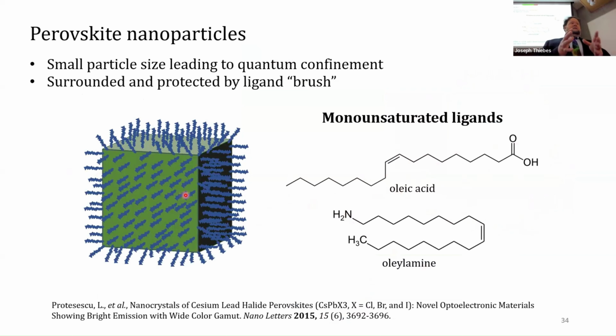And they put that in the synthesis process so that it stops the crystal growth when they're still very small. And these ligands are hydrophobic, and so they protect the crystal from degradation. The prototypical perovskite nanoparticle was synthesized by Protesescu and coworkers. And they used these ligands: oleic acid, which you find in olive oil, and oleylamine, which has the same backbone, but has the amine group instead of the carboxyl moiety.